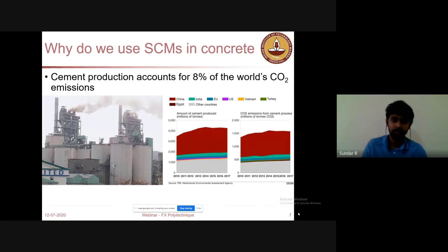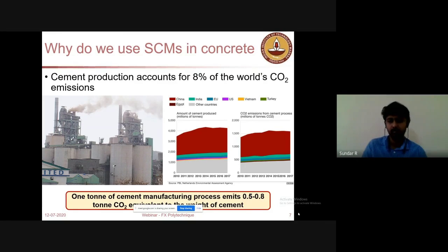If you see, cement production accounts for almost 8% of the world's CO2 emissions. This carbon dioxide emission is a huge challenge, and it contributes to global warming. As cement producers, as civil engineers, we should be concerned about it, because we use cement a lot, and we are contributing almost 8% of the world's CO2 emissions. Also, 1 ton of cement manufacturing emits almost 0.5 to 0.8 tons of CO2. So this is a huge amount. You have to see how you could reduce this, because for every ton of cement you manufacture, you are expelling about 1 ton of CO2.